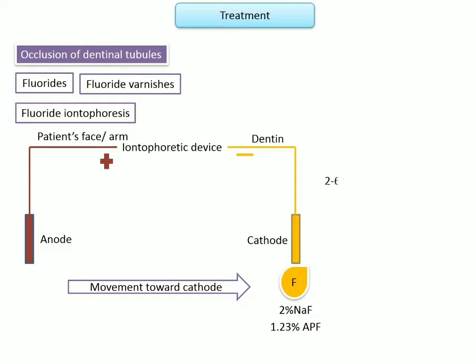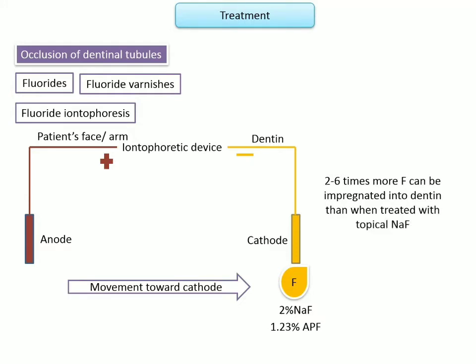The advantage of fluoride iontophoresis is that about 2 to 6 times more fluoride can be impregnated into dentin than when treated with topical sodium fluoride. So this provides immediate reduction in sensitivity after treatment with iontophoresis.